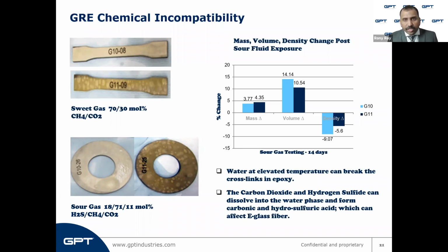In this case, G10 and G11 grade gaskets were exposed to sweet gas and sour gas for a period of 2 weeks. You can see from the bubbles forming on the gasket face that it appeared as though the G10 and G11 were being attacked by the sour gas.